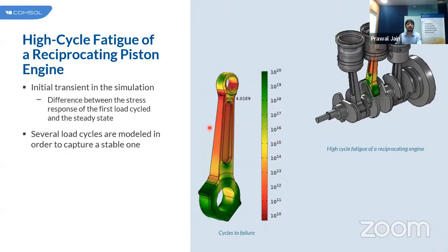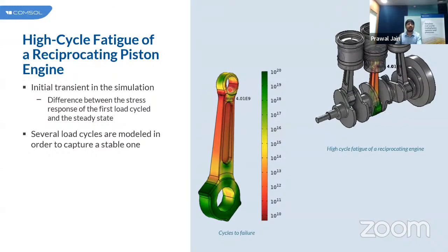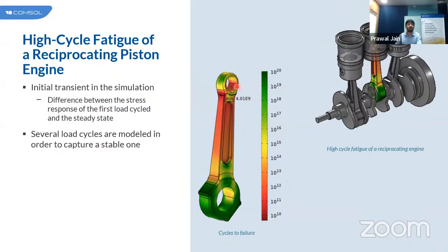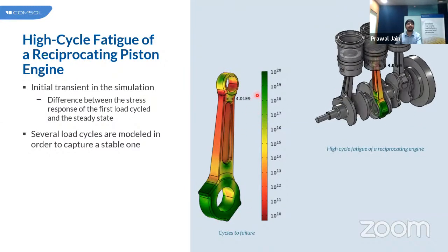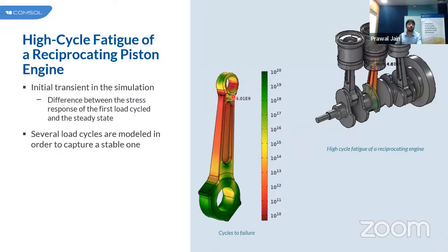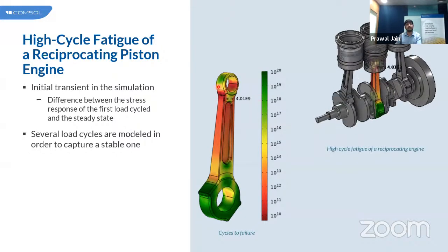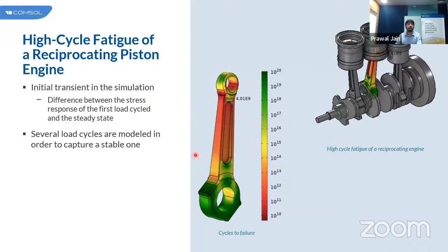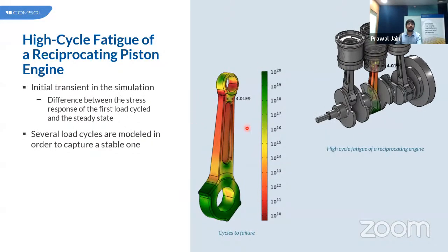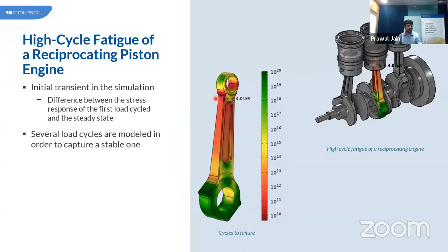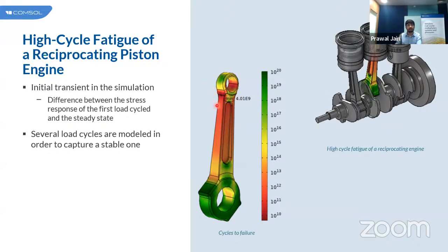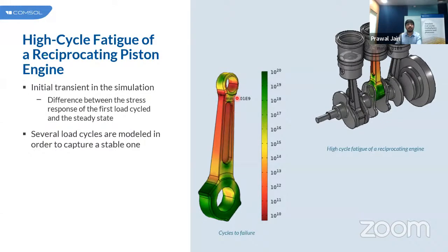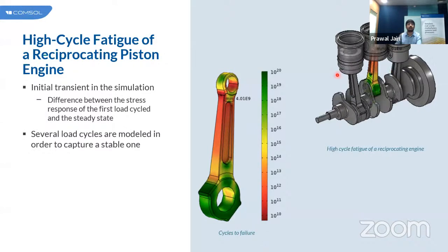Here we can see that the minimum life to failure occurs at around 4.01E9 cycles, while in the rest of the region it is significantly higher than at the fillet, where we can see quite a high stress concentration compared to the other parts of this connecting rod. So the connecting rod is most expected to fail from this fillet end, which is connected to the piston at the topmost point.